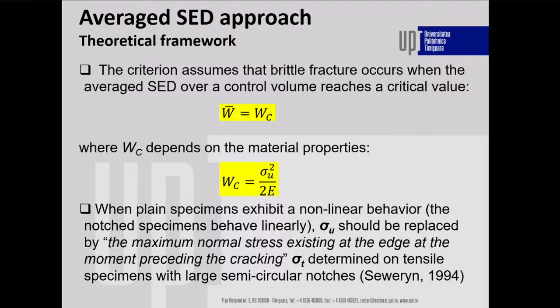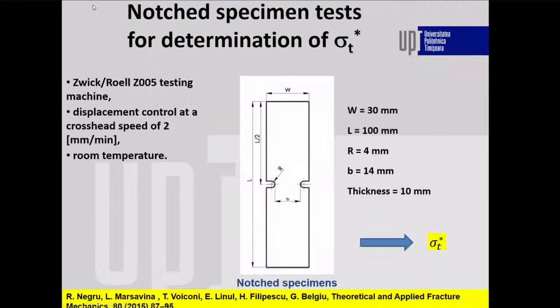So what we want to show now is that the average strain energy density approach can also be applied for this type of materials, and we replace the ultimate tensile strength of the material with the ultimate tensile strength of a notched component. This was determined by a student from Padua. He was in an Erasmus placement in Timișoara, and we used specimens with notches to determine the ultimate tensile strength of notched specimens.